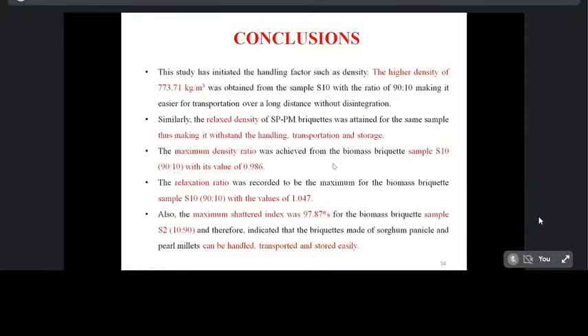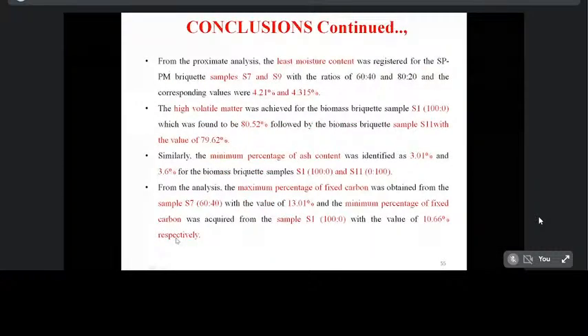The maximum density ratio was achieved from sample S10 as 0.986, and the relaxation ratio for sample S10 was 1.047. The maximum shattered index was achieved as 97.87% for the sample S2. In the proximate analysis, the least moisture content was achieved for samples S7 and S9 as 4.21% and 4.315%, and high volatile matter was achieved for sample S1 as 80.52% and S11 as 79.62%. The minimum percentage of ash content was achieved for sample S1 as 3.01% and S11 as 3.6%. Fixed carbon was achieved for sample S7 as 13.01% and S1 as 10.66%.